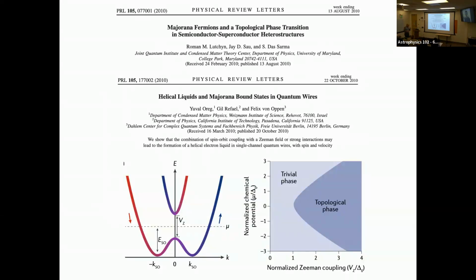So what happened next, and again, it took another decade for it to happen, is that the ideas of Kitaev, in particular this one at the end of the footnote about spin-orbit coupling, were not only formalized and written down, but numbers were put in for real materials. Like, we have a dilution refrigerator, it only goes to 10 millikelvin. Okay? We have aluminum that has a gap of 1.5 Kelvin. You have indium arsenide, we were just talking about in the previous talk, so we know what spin-orbit coupling is. How does it work out? If you actually plug in those numbers, do you get something where it's hopeful that you could stick it in a real dilution refrigerator with real indium arsenide and real aluminum and actually get something that would be measurable?